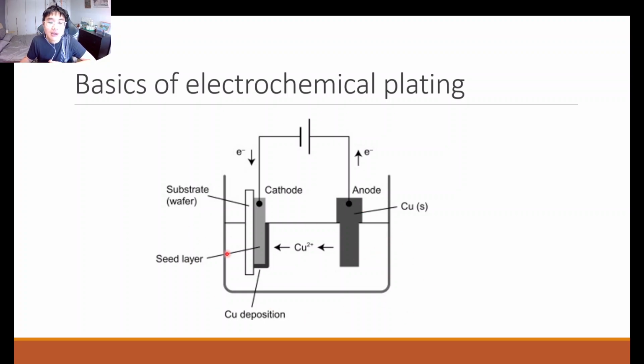And your electrolyte must be an ionically conductive electrolyte. So normally it is an aqueous copper salt, to provide a higher concentration of copper ions for the plating to occur on your cathode. And oftentimes it's also modified with other kinds of ionic species. Sometimes it's an acidic species like hydrochloric acid or maybe sulfuric acid. This helps to maintain a certain pH of your solution that may be desirable for certain properties, as well as increasing the ionic conductivity of your electrolyte. And why do you want to increase the ionic conductivity of the electrolyte? Because that reduces the internal resistance of your electrochemical cell, which allows for more energy efficient plating to occur.